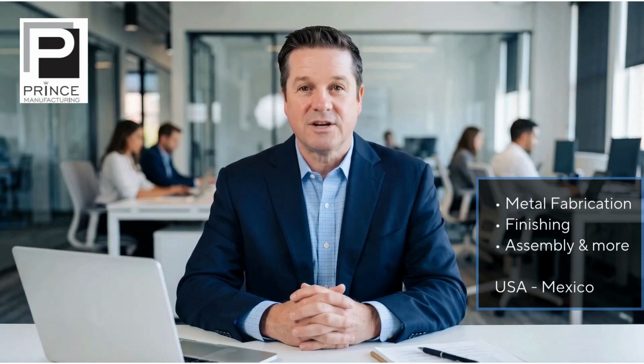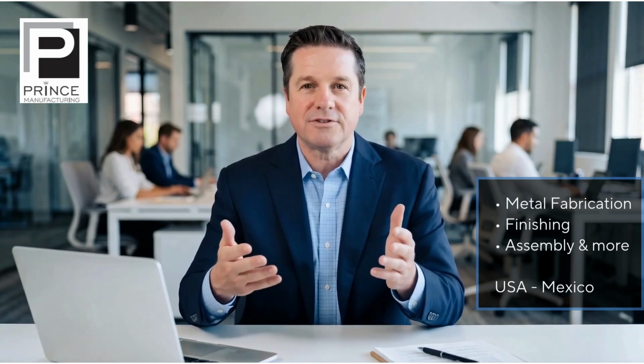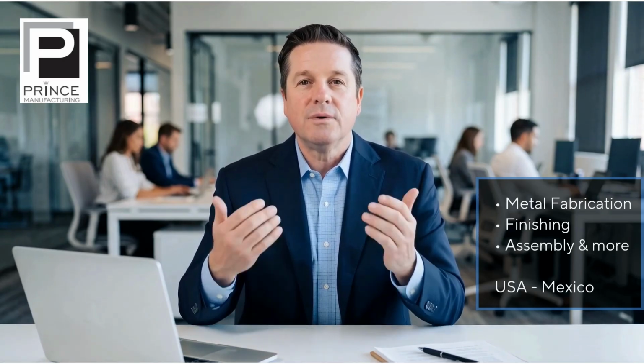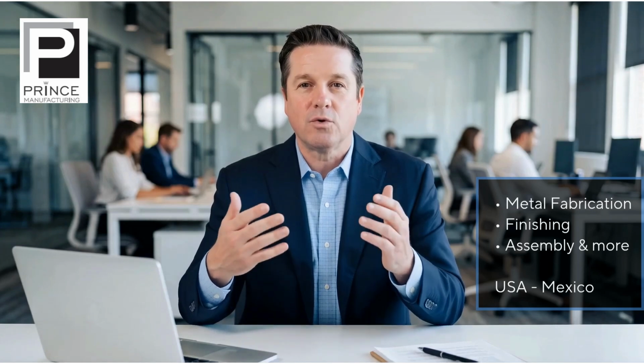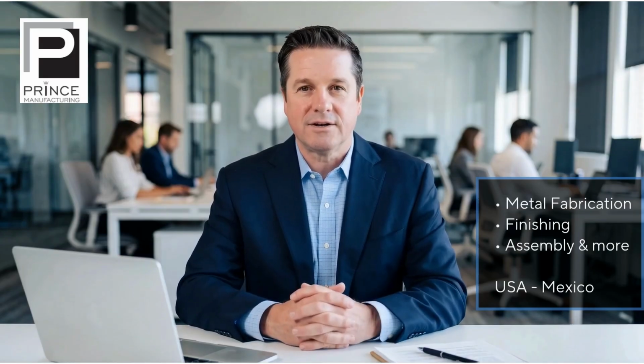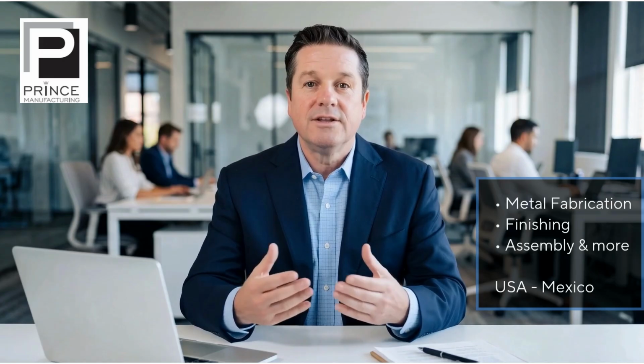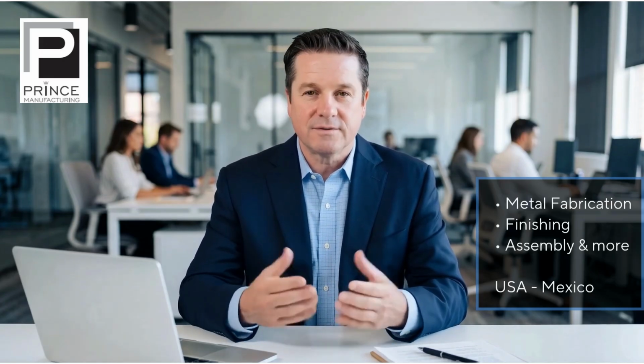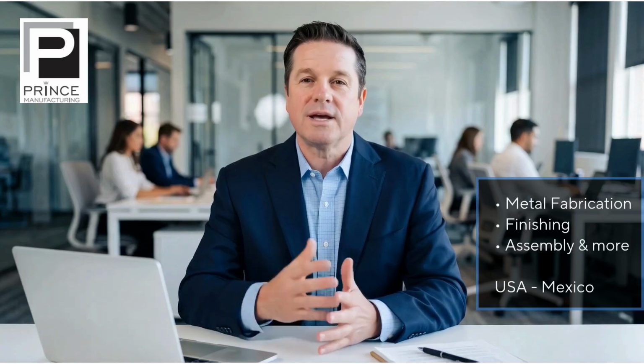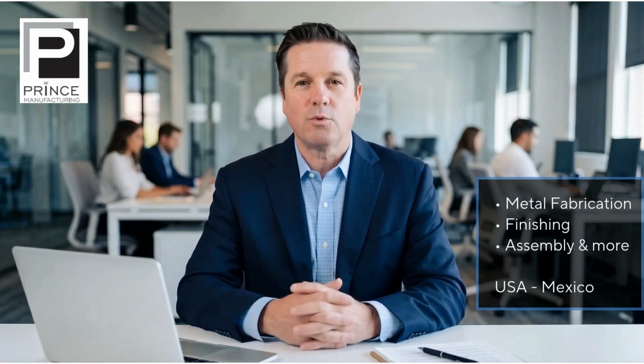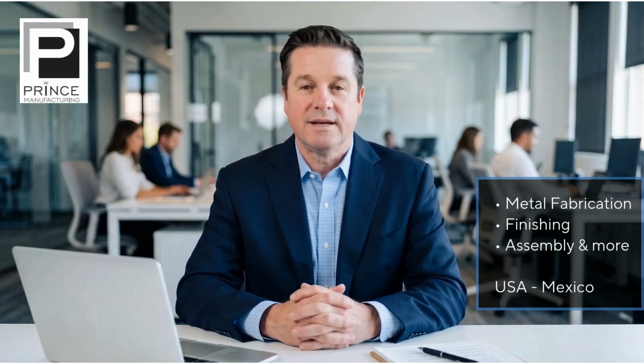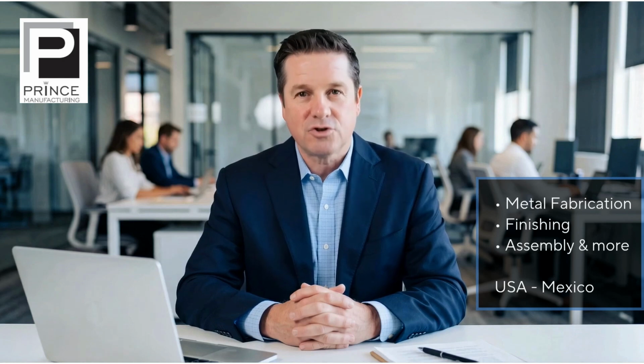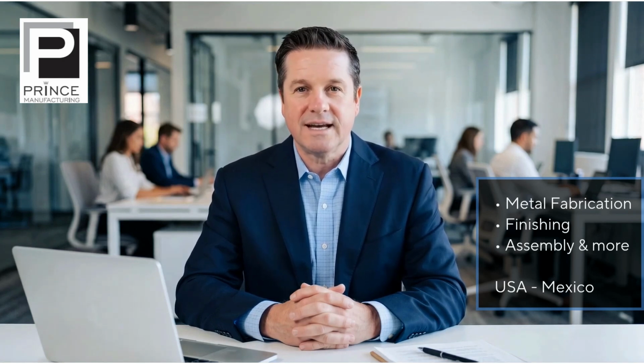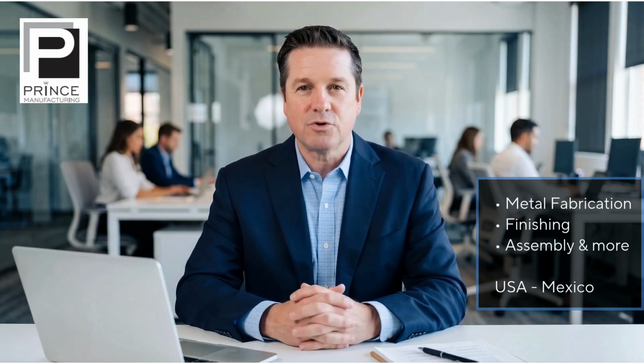The next consideration is the substrate. In other words, the material beneath the finish. Common substrates include low-carbon steel, high-strength steel, stainless steel, aluminum, copper, brass, cast iron, and galvanized materials. A finish that works well on carbon steel may require different pretreatment on aluminum. A process used on mild steel may create additional risks when used on hardened, high-strength steel. Copper and busbar components may need corrosion protection while preserving conductivity at designated contact points. Aluminum may require conversion coating, anodizing, paint, or a combination of treatments. The base material affects cleaning, adhesion, corrosion behavior, and the possibility of hydrogen embrittlement.